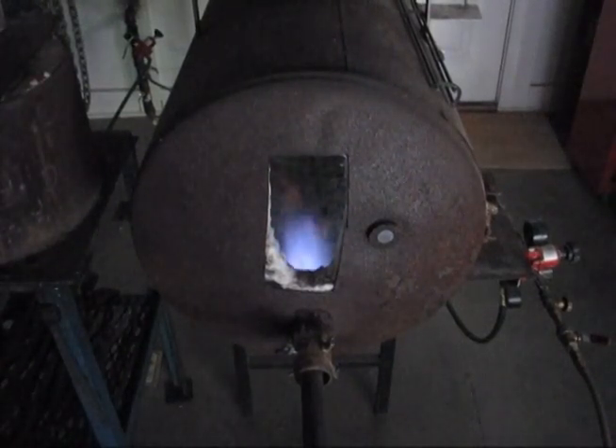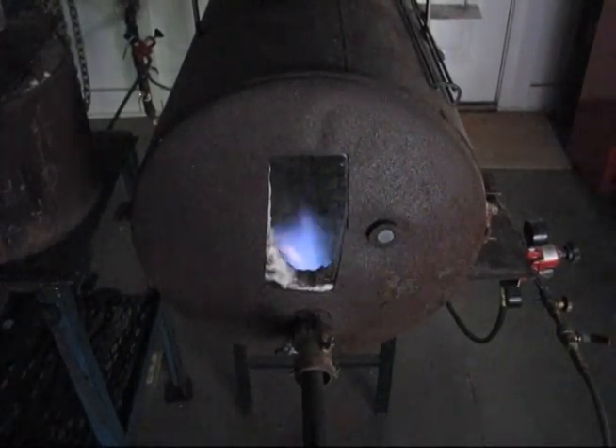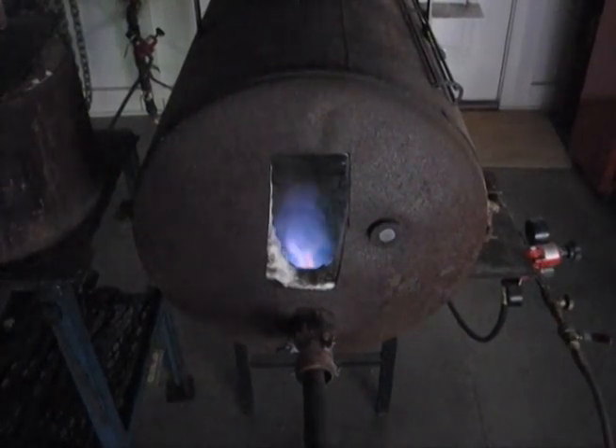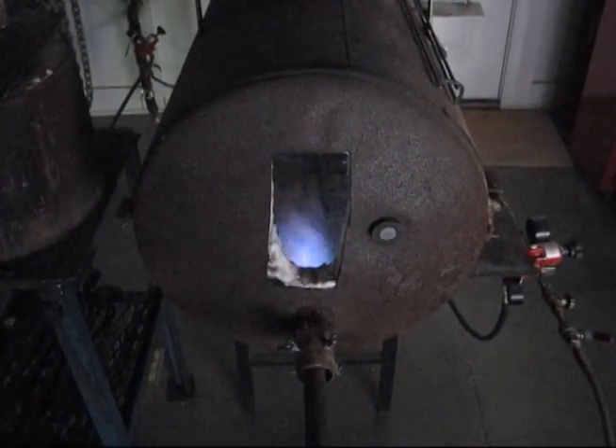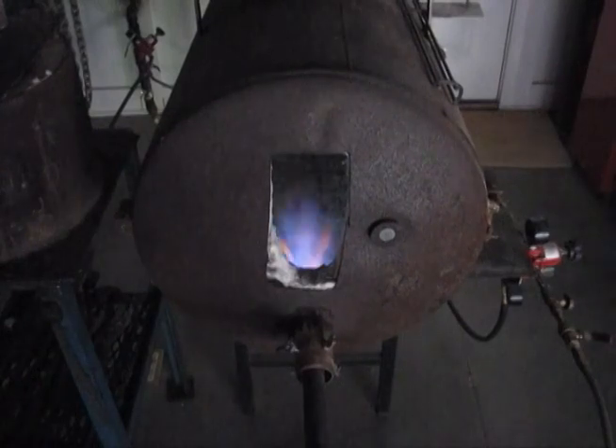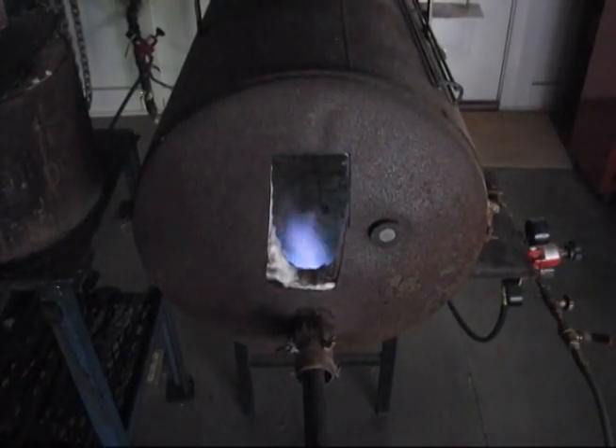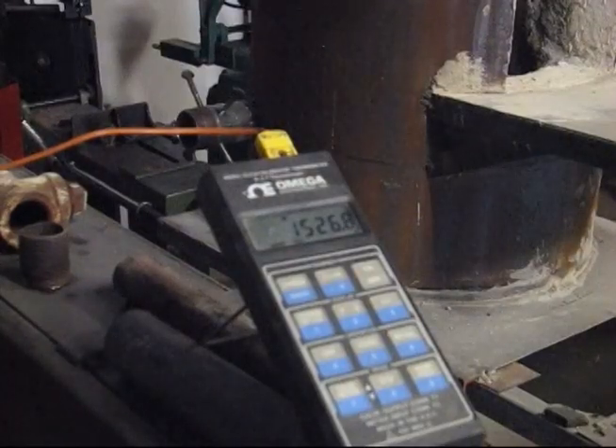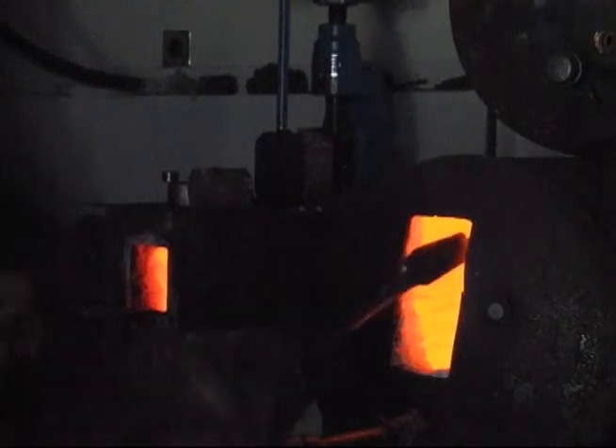This is a process consisting of bringing the blade to the so-called critical temperature, which corresponds to a fully austenite structure. A couple of cycles will be sufficient for a simple carbon steel like this. The heat treating oven is brought up to a temperature of around 1500 degrees Fahrenheit. The blade is placed inside and watched as it changes to a dull cherry red color and finally brightens up as its internal structure changes into austenite.